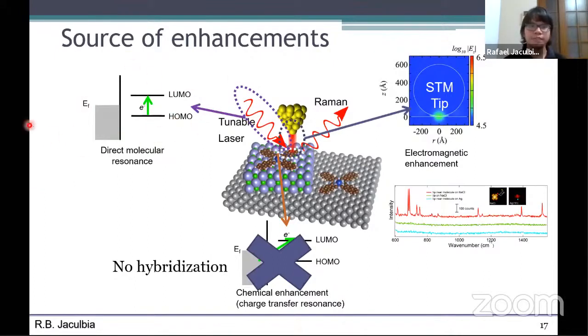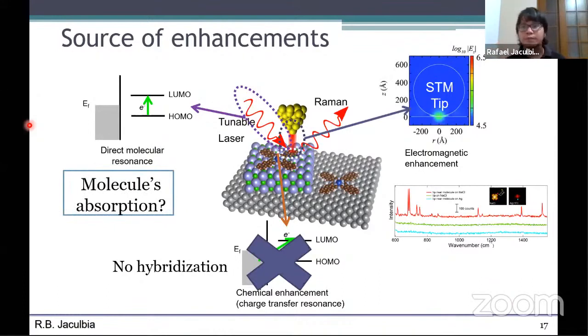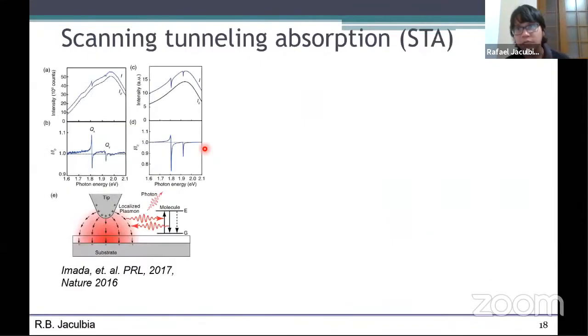But in order to confirm this, we have to determine the absorption spectrum of the molecule. I'm sure many of you are familiar that it's quite easy to measure the absorption of a molecule in solution or in solid form, but it's very difficult to measure the absorption of one molecule. Our group was able to introduce a technique. In conventional absorption measurement, you shine white light on the molecule and then measure the absorbed signal. Our group introduced a technique called scanning tunneling absorption, wherein the localized plasmon resonance at the tip-substrate junction also has a broad spectrum.